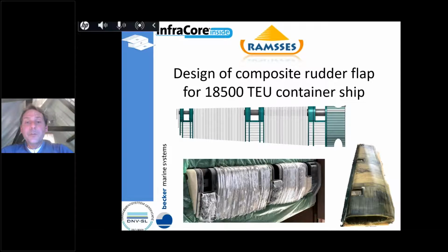And then we produced a scale 1 to 6 rudder flap because we could well have produced a scale 1 to 1, because again, size does not matter for us, but you should be capable of testing such a thing. And this rudder flap has, just to give you a bit of a feeling, 100 tons per square meter loading. So it's a heavily loaded beast. So in order to test it in an ultimate way, so up to failure, scale 1 to 6